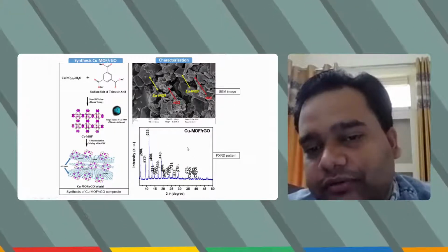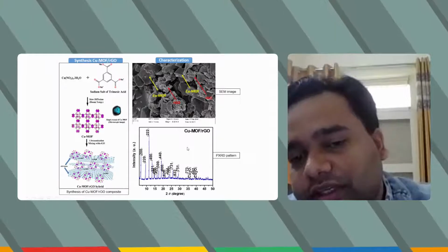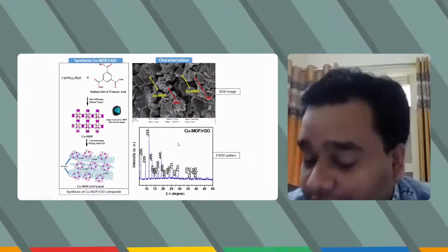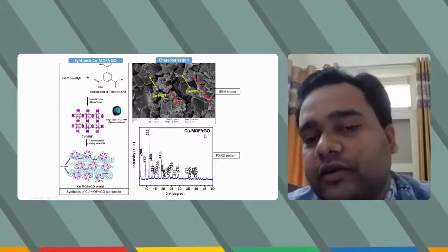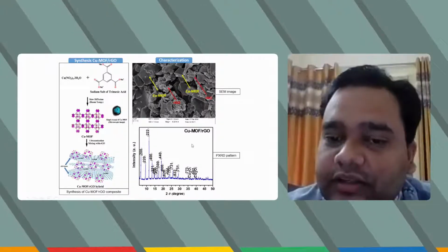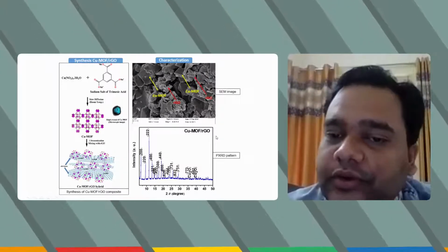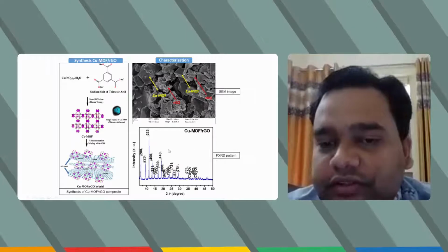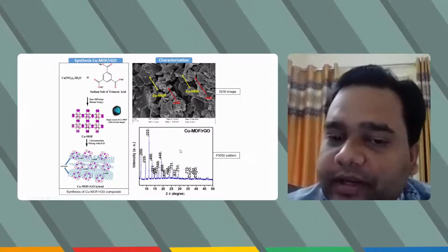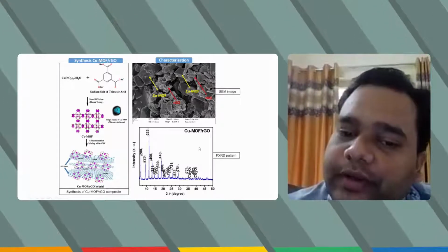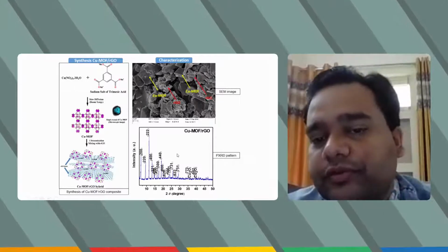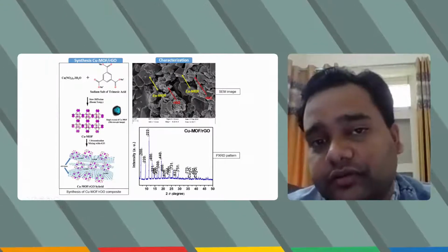And this is the XRD of the copper MOF RGO composite. You can see this XRD pattern is also alike to that of the copper MOF. So it says that on introducing RGO, the crystal structure of copper MOF is maintained. It has not destroyed the crystal structure of copper MOF, which is very beneficial for a composite.